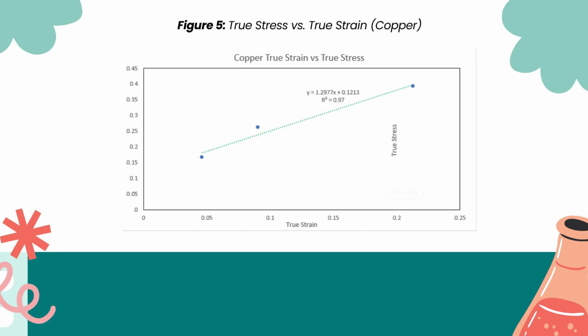Plot of copper, true strain versus true stress. We are looking at the material's flow curve. Notice how the line slopes upward. This is strain hardening in action. As we stretch the copper, increasing the strain, the internal structure becomes more tangled with dislocations, meaning we have to work harder and apply more stress to keep it deforming. Our linear model shows an R² of 0.97, proving that for this range, the relationship is very predictable and consistent.